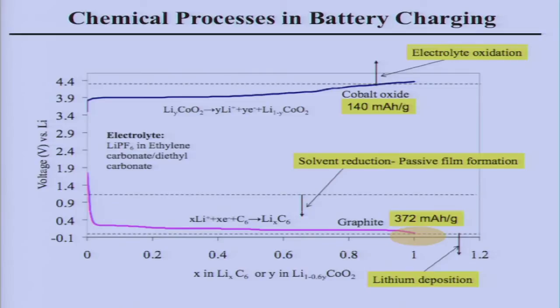Below roughly 1 volt, the organic electrolyte is not stable. It is going to decompose, reducing the organic electrolyte and forming the so-called SEI layer, solid electrolyte interface. You want this layer to be self-passivated. Then you start to put lithium and electrons into graphite carbon. You store a lot of them, but make sure you don't go below 0 volt versus lithium metal. Otherwise, you start to plate out lithium metal. It grows dendrites. It's going to cause shorting, fire, explosion. This is the negative electrode side.